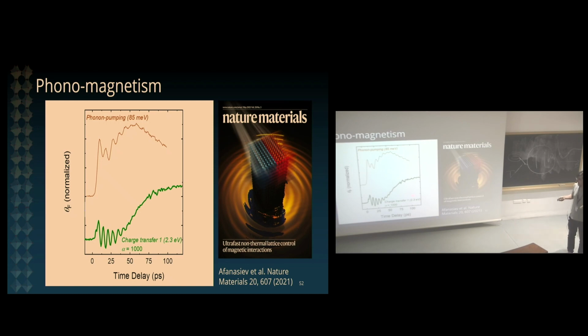So you can take the same material, and instead of exciting the lattice, you can excite a charge transfer resonance at much higher photon energy, of the order of 2.3 electron volts. And you see that with these electronic excitations, you indeed, again, excite a spin wave that oscillates around 0, and then heat is being redistributed into the system, and it eventually reaches the lattice degrees of freedom, which excites the system across the phase transition, and the system starts to develop a net magnetization. Okay. And this takes something of the order of 100 picoseconds to occur. So you need to diffuse heat across your system.